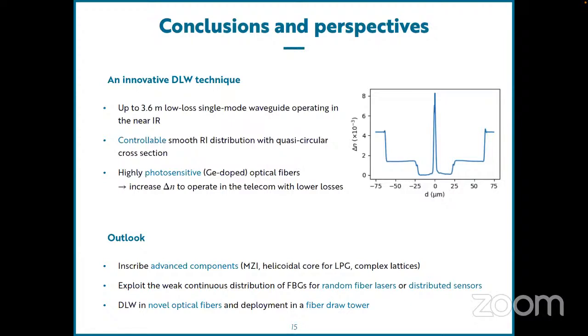We developed an innovative direct laser writing technique. We managed to really write for the first time very long waveguides, which are low loss and single mode, and they operate in the near infrared. We can control the value of the refractive index, which is quite smooth and quasi-circular in terms of the cross section, and we can also use hydrogen loading to have a good control on the refractive index.